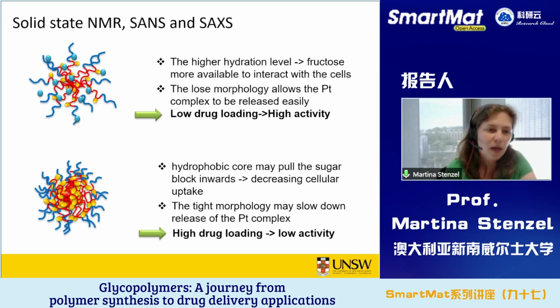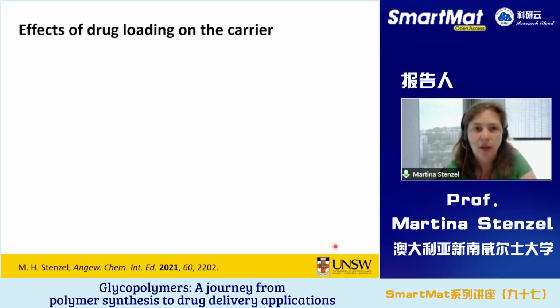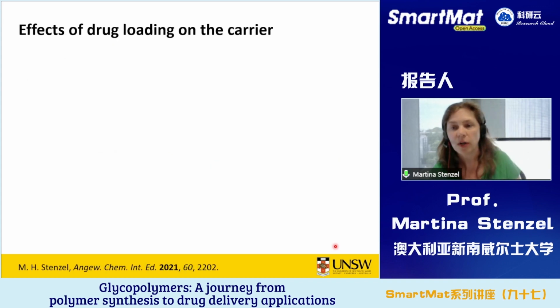However, if we have a lot of drugs in the core, a lot of drugs make the nanoparticles very, very hydrophobic. And because they're very hydrophobic, as a result, the nanoparticles are less hydrated, and they have usually more protein on the surface. So if we have high loading, we have low activity. And this is something we observe over and over again.